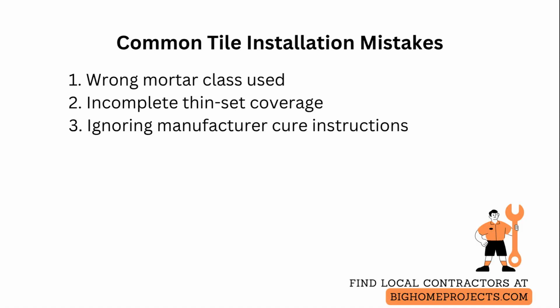Using a non-modified or mastic product on a cement floor will often fail, so switch to a polymer-modified thin set that matches tile size and expected loads. Allowing tiles to sit on trowel ridges without back butter leads to hollow spots and eventual cracking, so butter large or uneven tiles and check for full transfer.